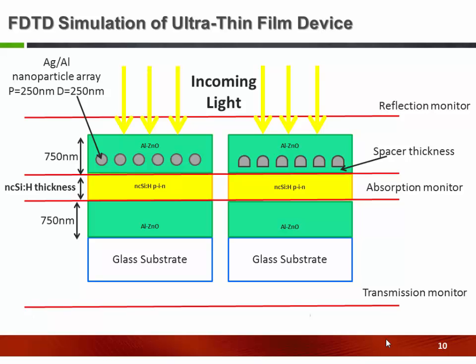That's a simulation. But in reality it's very difficult, because you would have to synthesize just a-SiO, silver nanoparticles embedded in a-SiO, measure the absorption there, and then subtract that from the absorption of, for example, the metallic structure. But it's not very accurate, because the final device is different. Simulation gives you an idea of what you will see later in real devices, because I have seen it. Right now we are in the middle of making these devices, and we see exactly the same answer as in the simulation.